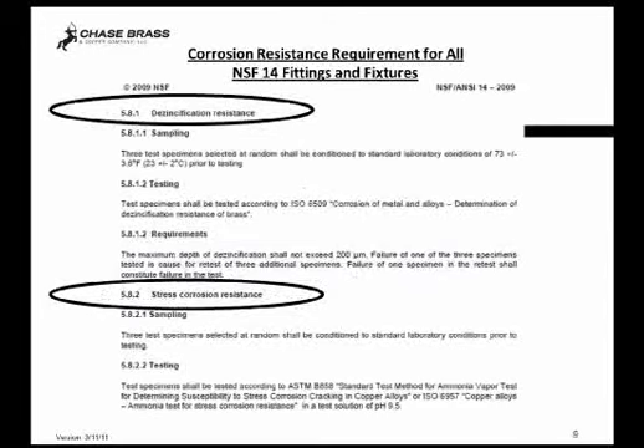The types of materials that are used for PEX fittings, as a result of some significant field failures over the last few years, NSF 14 now incorporates a dezincification resistance requirement as shown in the upper oval here. And that means that in a standardized international type test, parts cannot exceed 200 microns in depth, and that's 0.008 inches, 0.008 of an inch in that standardized test. If it does so, then it fails.